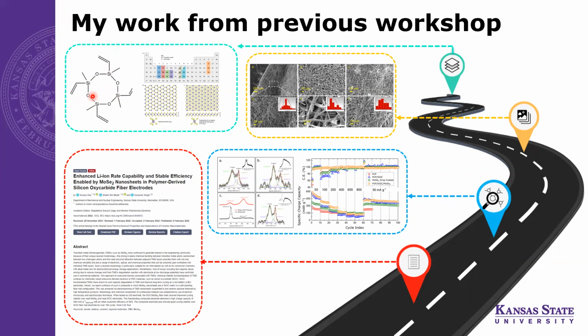These materials were then examined via spectroscopic and microscopic techniques, which revealed the chemical bonds present or the morphology of the fibermats. Finally, these fibermats were used as a freestanding electrode in a lithium-ion half-cell setup, which showed improvement in stability as well as capacity compared to other electrodes. This work was published in a high impact factor peer-reviewed journal early this year.